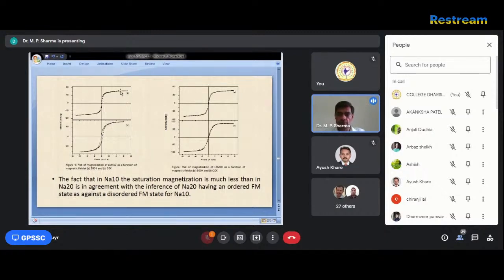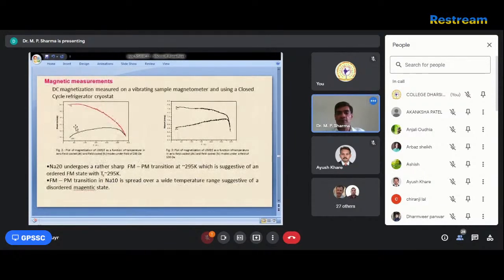So for a low temperature, another is a room temperature. A and B, one is for a room temperature, another is a low temperature, 20 Kelvin. Both of the samples have to be taken at the room temperature and 20 Kelvin. In effect, in sodium 10 the saturation magnetization is much less than in sodium 20, which agrees with the inference of sodium 20 having an ordered FM state against the disordered sodium 10. So we can say using this magnetization that at this point it is ferromagnetic, but in this one it is nearly, but the system is ordered.